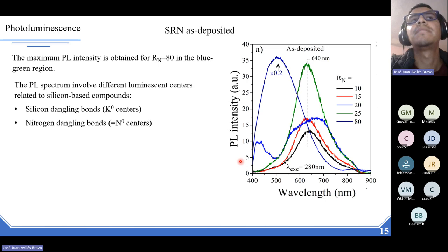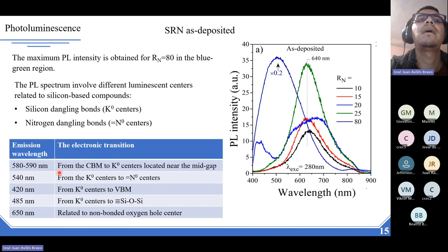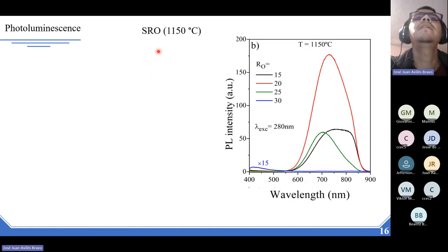The photoluminescence spectrum involves different luminescence centers related to silicon-based compounds, principally silicon dangling bonds and nitrogen dangling bonds. The spectrum of the photoluminescence shown in this figure exhibits all the electron transitions. In the case of the silicon-rich oxides annealed at 1150 degrees Celsius,